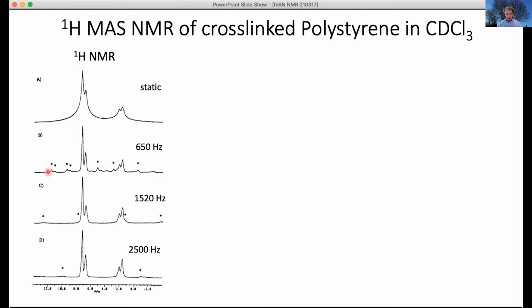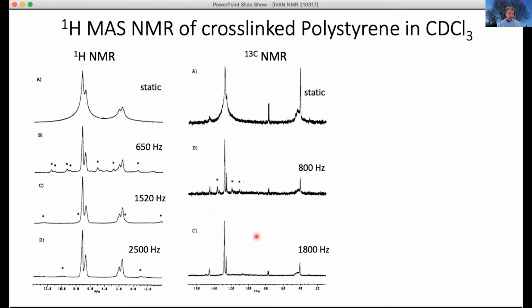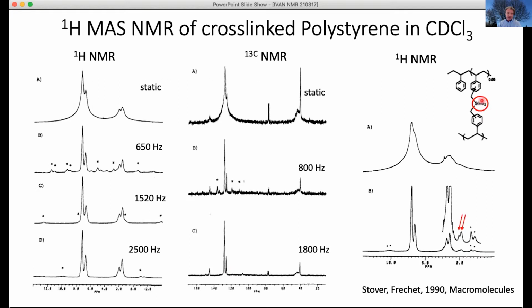Spinning sidebands move out as you spin, still relatively slowly. So you can get proton and carbon NMR without any cross polarization - you can get highly resolved solution-like spectra. In chemistries where you have a functional group at the cross-link, this is a dimethylsilane cross-linker, you can even resolve different features of that cross-link at 0 ppm.